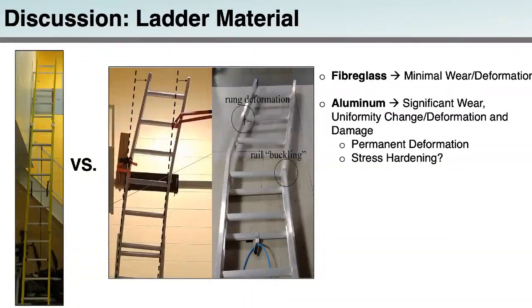Throughout the conditions tested, there was minimal wear, uniformity, or change in deformation to the fiberglass ladder. The only visible damage, as I mentioned earlier, was that the fiberglass ladder showed some slight fracturing around where the rails inserted on the ladder. Despite the one instance of rung failure, across all trials tested, there was minimal buckling or deformation. The most drastic deformation was in the 90-degree rightward, so that directly horizontal force direction. However, in these conditions, there was visible flex in the ladder rails in the direction of the pull force. However, once we removed the 250-pound load, the fiberglass ladder rails quickly returned to the original position with minimal deformation. This can be seen here again in the image of that fiberglass ladder that had been exposed to all 42 different drop test conditions.